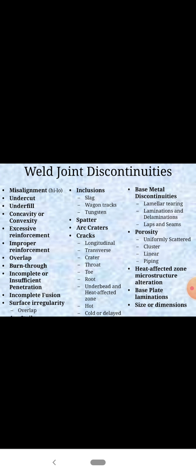So there are general sources of defect for most of the conventional arc welding processes, leading to improper selection of the process. If we are using a deep penetrating heat source, or a narrow V angle, it causes cracking in the root run due to the large depth to width ratio. Another cause is the incorrect application of current, and shielding gas use, of the weld metal deposition, and so on.